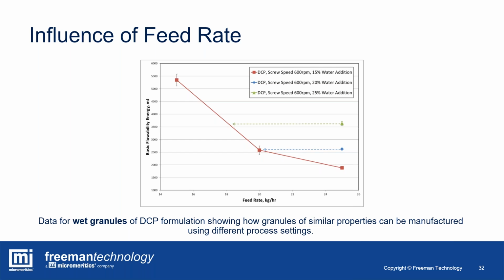And what you can see here, this example at 20 kilograms per hour with a 15% water addition has the same attributes as that at 20% water with a higher feed rate. So by manipulating your process parameters, you can identify how they influence the attributes of the material that are coming out of that process step. And of course, that gives you a substantial step towards being able to employ a quality by design approach of identifying critical process parameters and using those to design in attributes that you desire in your finished product.